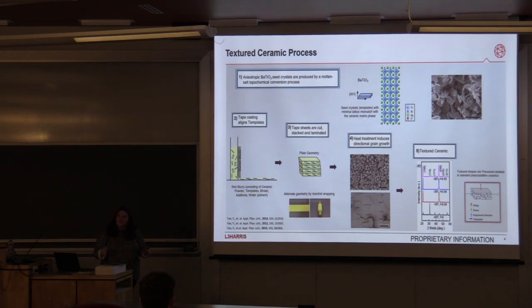Once we've grown those, using slightly different than usual metal oxide ceramic manufacturing processes, which I'll touch on in a second, we're going to use something called tape casting. What we're going to do is you have your slurry, which is made up of your ceramic, which is actually most of the content of it. Then you're going to add a small amount, maybe 5% or less, of these templates, very, very small. And then you're going to add some binder additives and a solvent, in our case water, because it's just more environmentally friendly.